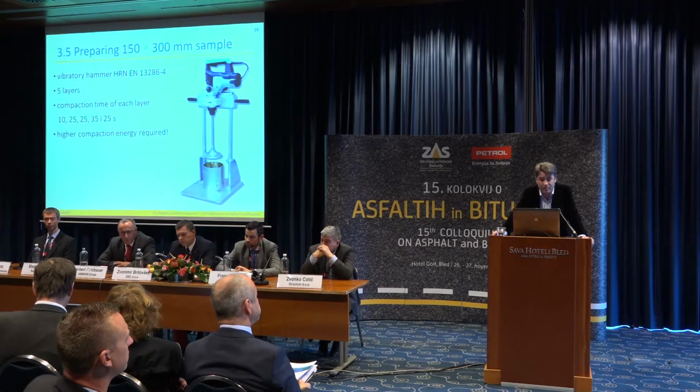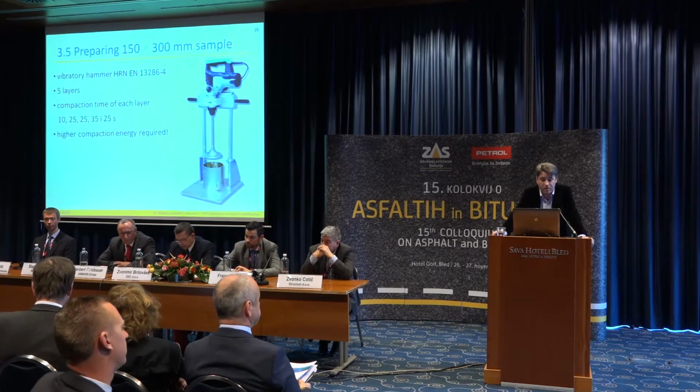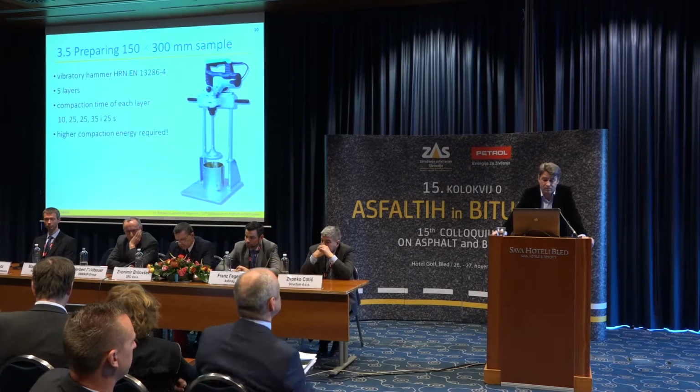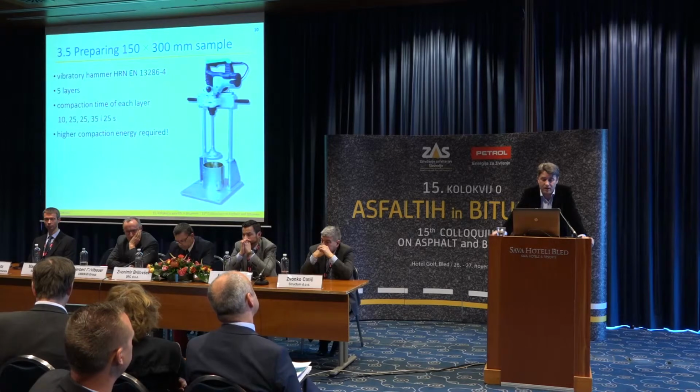Preparing a sample of 150 by 300 millimeters was done with a vibratory compactor that is described in a European norm for a modified Proctor. We did it in 5 layers, so it's approximately 6 centimeters a layer, and each layer was compacted with a different compaction time.